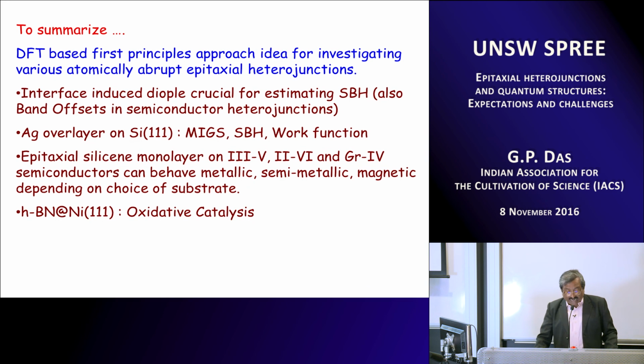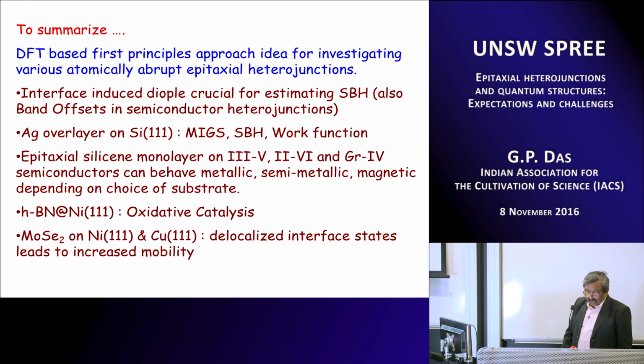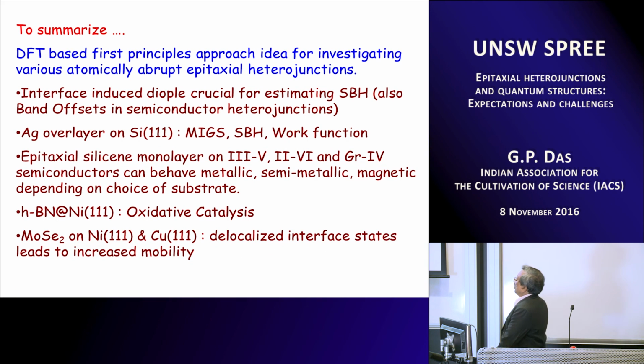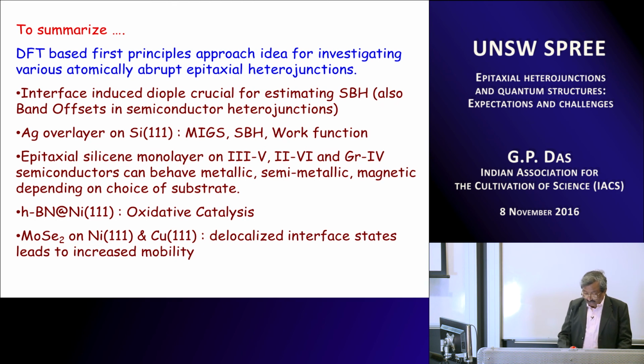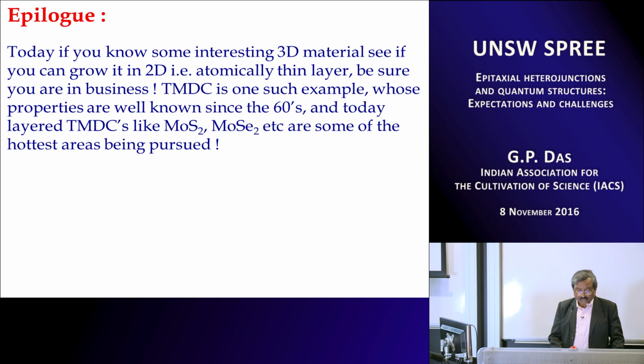And towards the end, I told you about the hexagonal boron nitride on nickel 111, which serves as an oxidative catalysis. And finally, the molybdenum diselenide on nickel 111 and copper 111 is an example where the delocalized interface states lead to increased mobility and also chemical functionalization of the surface. So that is where I end my lecture today.